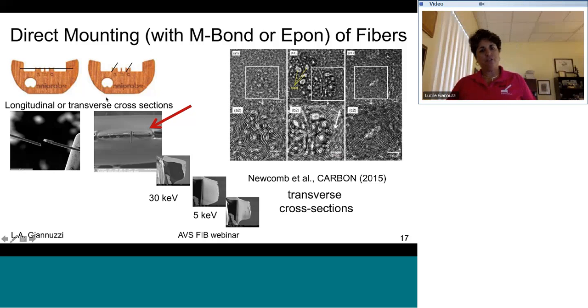It turned out that the transverse cross-sections were a lot more useful to look at. So I actually had the grad student glue these small pieces of fiber perpendicular to the original grid. I'll show you a better way to do this, but this was done basically by hand with tweezers using a stereoscope. And then you just start to FIB mill from both ends until you're left with an electron transparent specimen. I'll describe these different methods in detail later when I talk about low energy polishing. But just finishing with 5 kV gallium, we can look down these carbon nanotube pores pretty nicely.